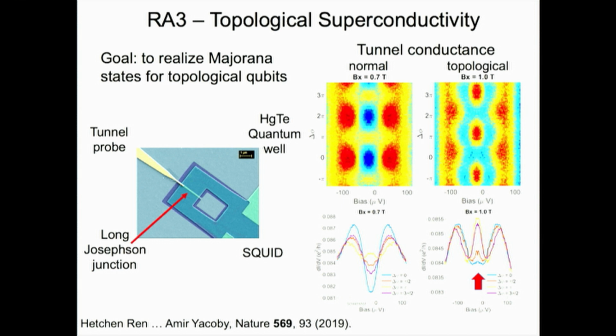And so you can move them quite far from each other, and then you can have a particle run into the one on the right, and it won't disturb the state that it's in. Okay. And so that's the challenge, and there's been some things, Charlie Marcus, Leo Kouwenhoven, I think, was the first that saw evidence for that in nanowires. But it's still sort of up in the air because not everybody can reproduce the results, and there's a lot of arguments about how to do it. So what Hetchen did was to actually make it out of a two-dimensional material where this is changing the density and then the phase difference.